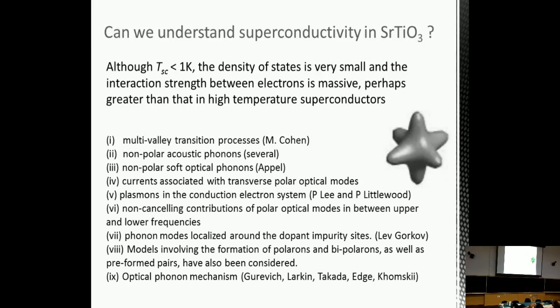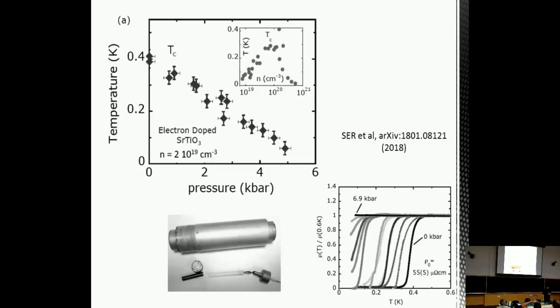Non-cancelling contributions of the polar optical modes in between the upper and lower frequencies, phonon modes localized around the dopant impurity sites. These are kind of a local phonon picture by Gorkov. And then also there have been models involving the formation of polarons and bipolarons. Preformed pairs have also been discussed. And then the final one, of course, is what about the optical phonons? And this also has a long history, starting with Gurevich, Larkin, and especially Takada in the 1980s. So we thought we would do some new experiments to try and get a handle on what's going on.